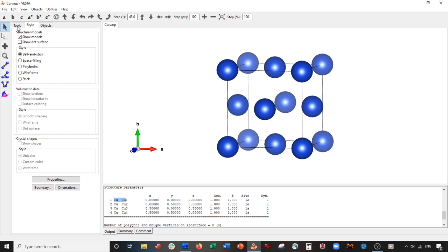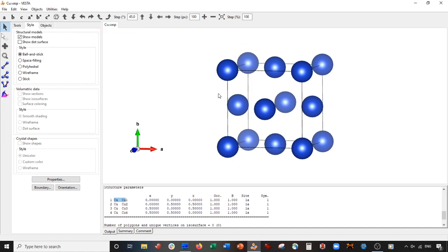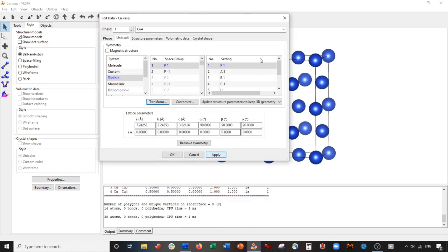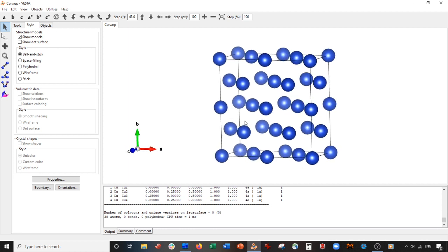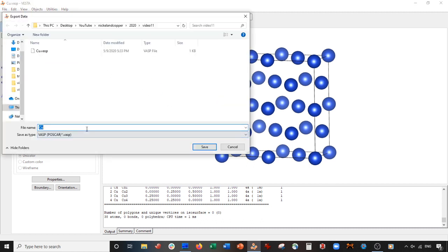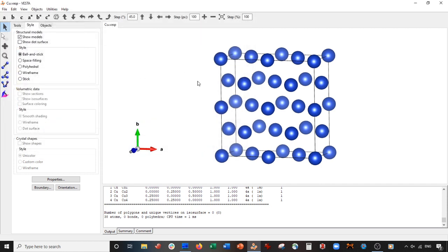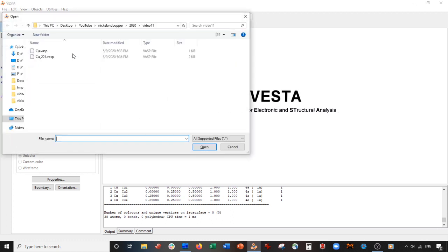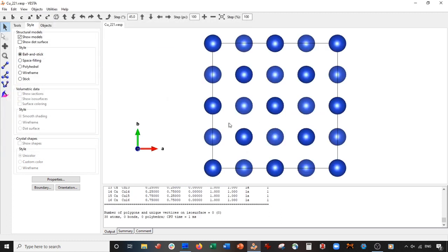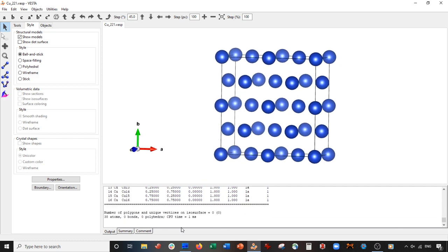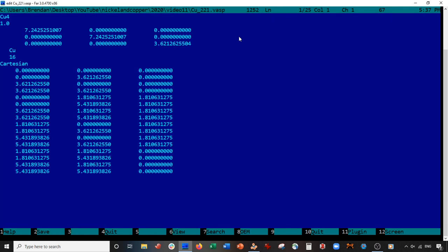And what we're going to do, to do that, we're going to go to Edit, Edit Data, Unit Cell, hit Transform, and we're going to transform just the A and B vectors. And this is going to give us a unit cell with approximately 16 atoms. Now it doesn't really matter which vectors they were because we have a perfectly cubic unit cell. So now what I'm going to do is save this, this is very important. And you're actually going to export as a VASP. So we'll do copper and we did a 221 expansion.vasp. Hit save, Cartesian coordinates. Now I'm going to close this with Control W, open it with Control O. Okay, now you can see we have 16 coppers. If we go over to our text editor, this should show up here as well. So you can see we have 16 coppers and the lattice vectors have officially been scaled.